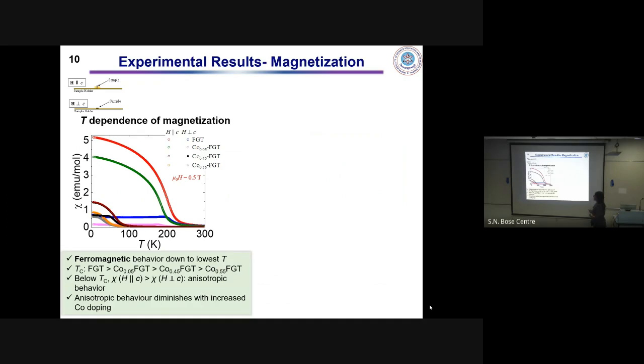So moving on to the magnetization measurements, here you can see the temperature dependence of magnetization. From the M versus T curve, we can see this red curve corresponds to the magnetic susceptibility curve for FGT when the magnetic field is applied along the c-axis of the sample. And this blue corresponds to the configuration where the magnetic field is applied perpendicular to the c-axis of the sample. As we are going down from room temperature, we can see there is an upturn around 220 Kelvin, which marks the onset of the ferromagnetic behavior. And we can see there is a large difference between the red and the blue curve, which indicates there exists magnetic anisotropy in this system.